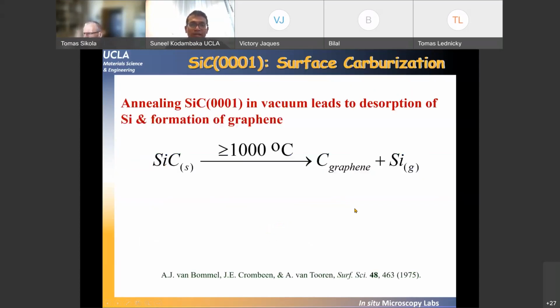For those of you that are not familiar with this concept, you take single crystal silicon carbide, and if you heat it in vacuum or in inert atmosphere to high temperatures, carbon stays on the surface, silicon preferentially desorbs, and so you can get graphene, or if you do it for longer times, you will get graphite. And this phenomenon was observed a long time ago, and in recent years, this process has been used to controllably grow either monolayer graphene or bilayer graphene.